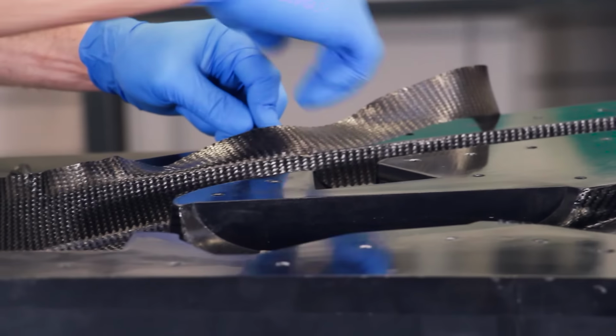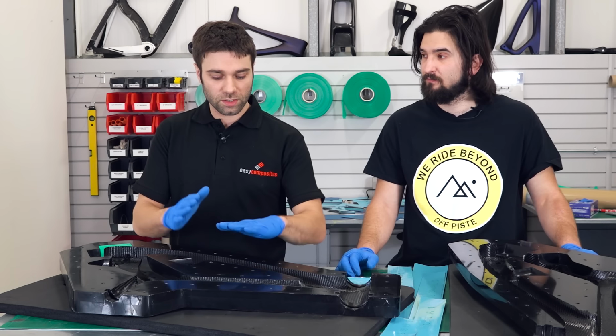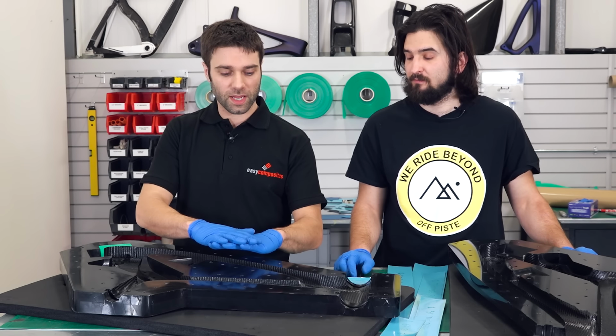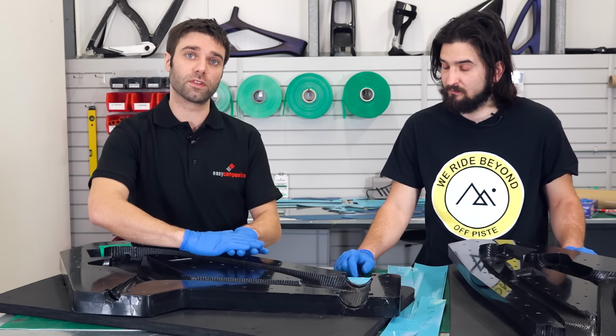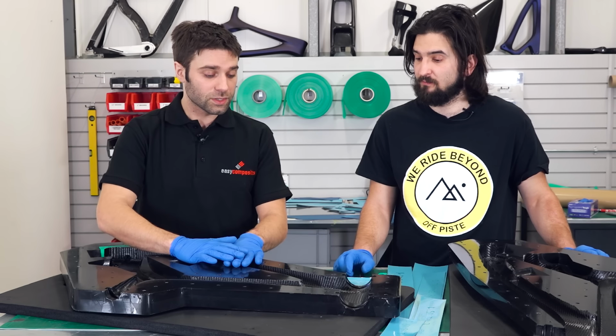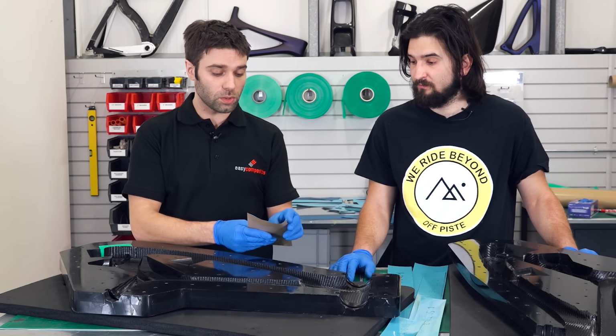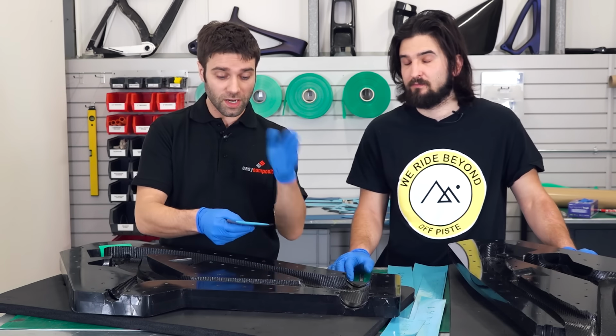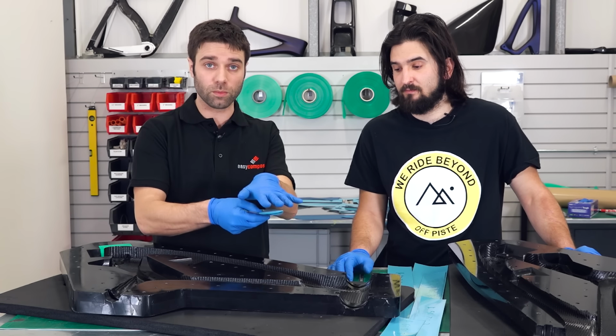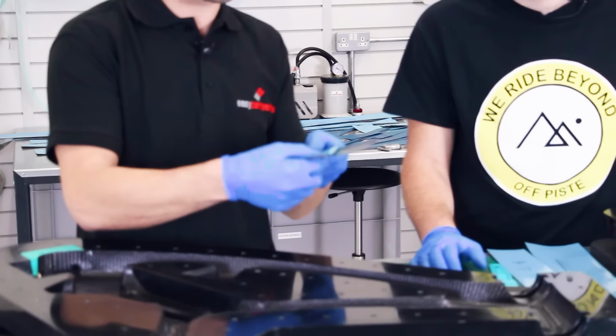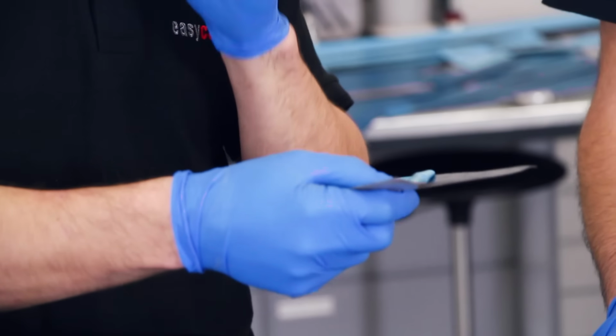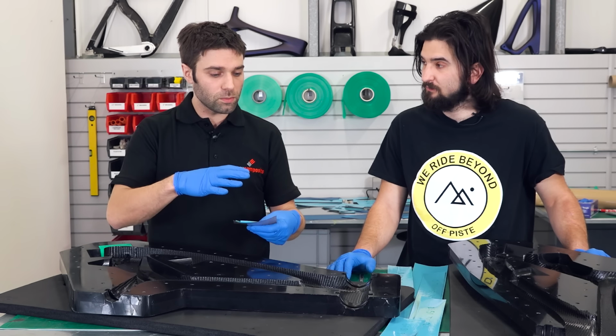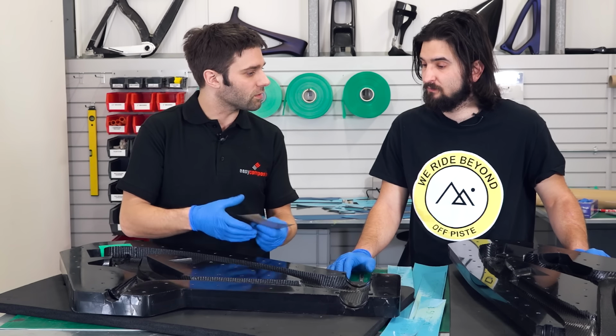So we've got the first two plies into the mould. So we have the 0/90 woven fabric and then the plus minus 45 degree woven fabric after that. So the next layers to go in are unidirectional carbon. Now, unidirectional carbon has all of the fibres running in one direction, which means all of the strength, or nearly all of the strength, is running in that direction.